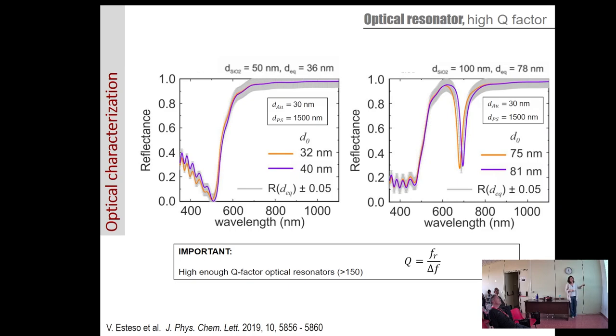Whereas these two other systems are out of equilibrium. These are just pictures of it. These two cases lie inside the gray curve, meaning that I could not distinguish a system in equilibrium from those out of equilibrium. Whereas in this other case, we have another two systems out of equilibrium. This is at equilibrium. The quality factor is around this, and then we can distinguish this minimum from these two others.